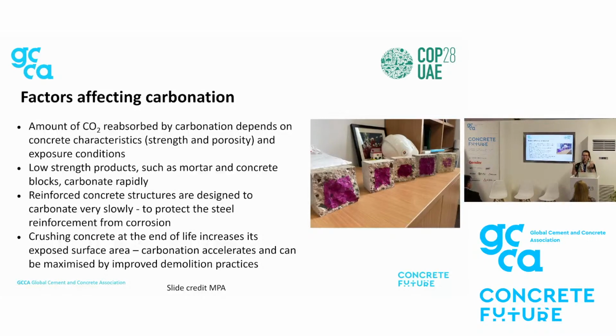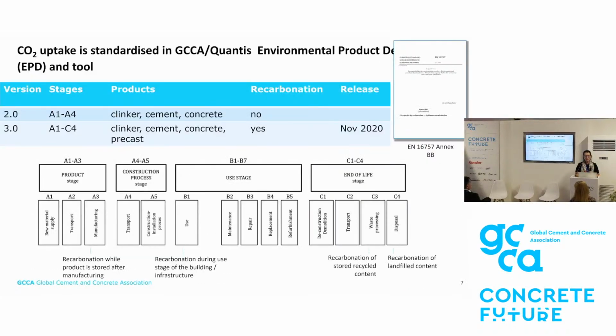Actually, it's important to highlight that this phenomenon has been known for decades, and it's something structural engineers have been fighting, because carbonation was creating problems with the steel reinforcement and corrosion of steel reinforcement. So concrete has been designed not to carbonate too much when it comes to reinforced concrete, but still the surface is recarbonating, and then, as I said, at the end of life, crushed concrete recarbonates more.